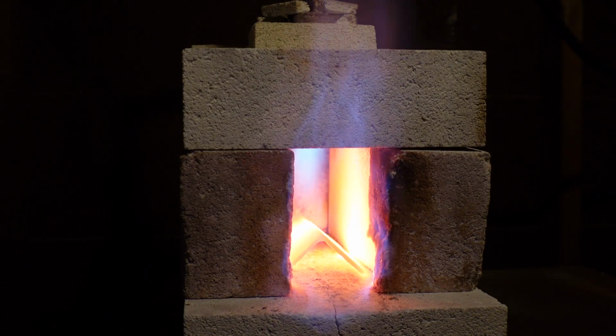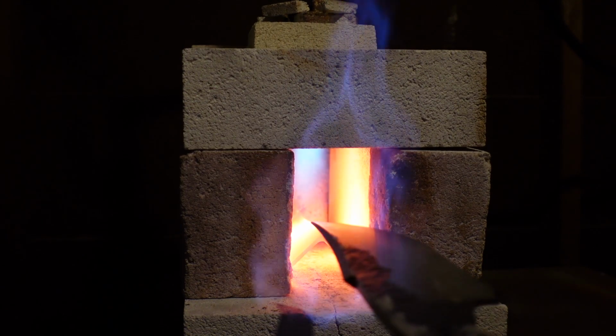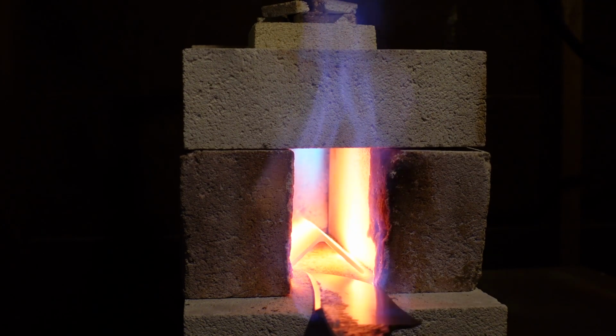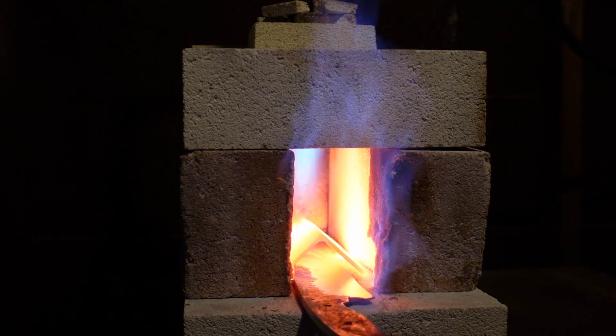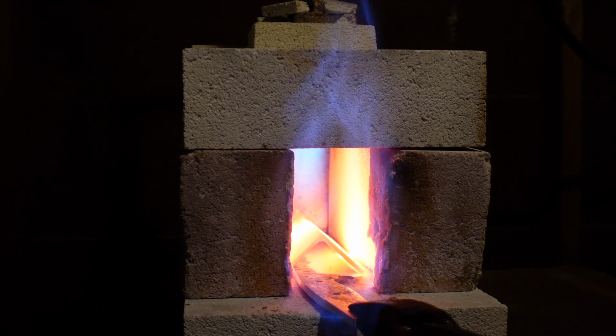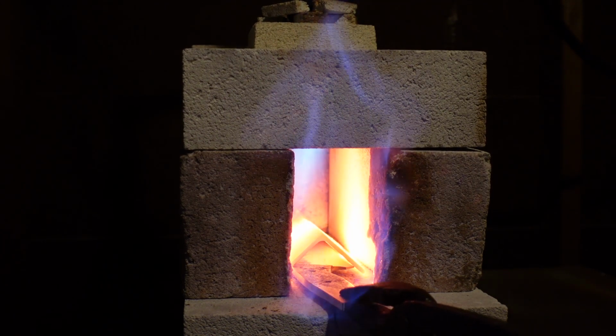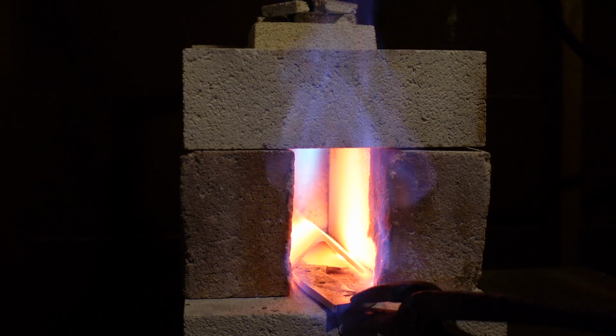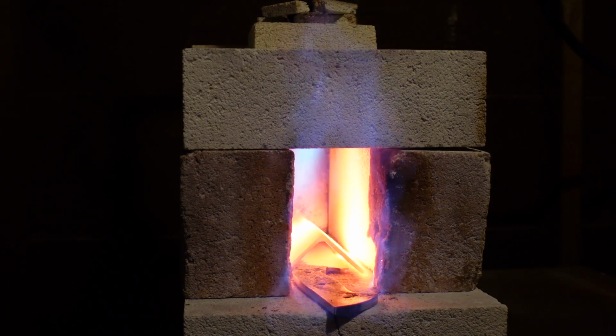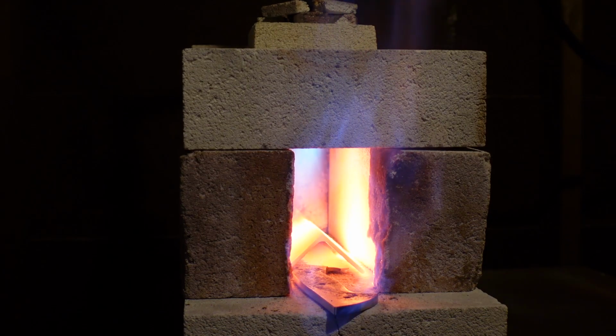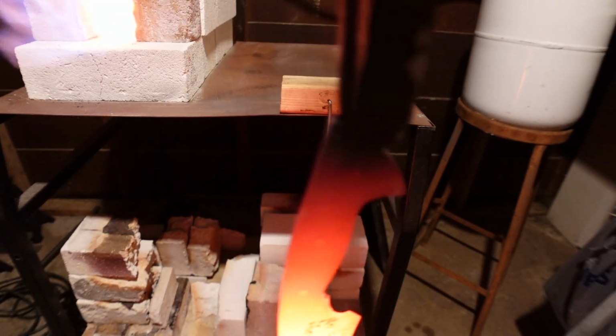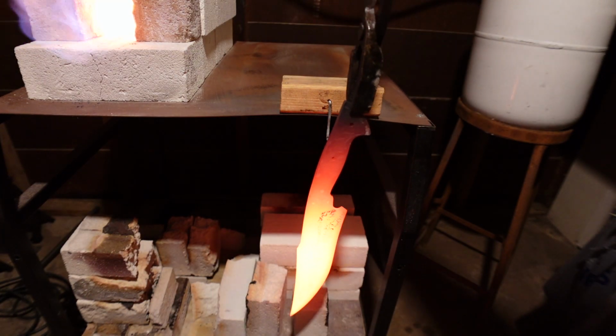As you can see here, I did put a piece of angle iron inside the forge to act as a baffle to disperse the heat around the forge so I didn't have that flame directly on the blade, creating an unnecessary hot spot. You want to make sure that your blade is heated evenly, especially during these normalizing cycles, so that the normalizing cycles can do what they need to do.